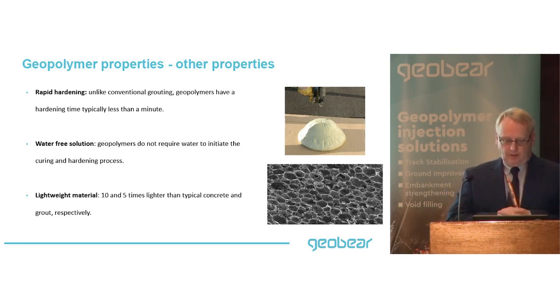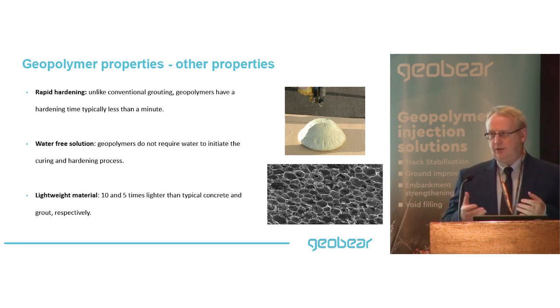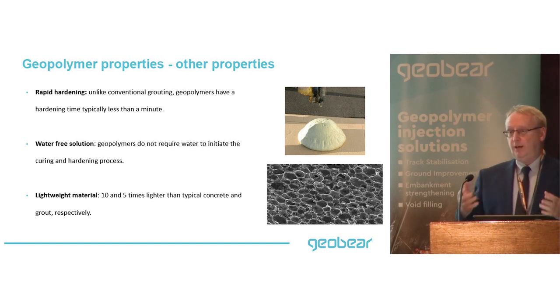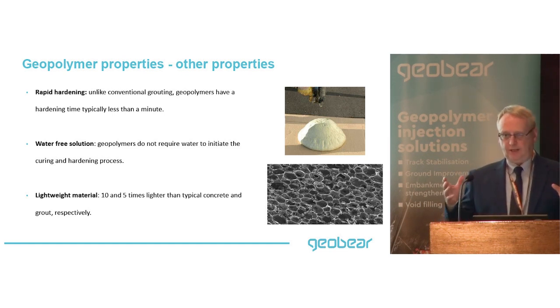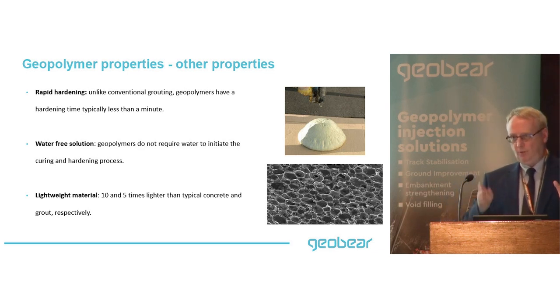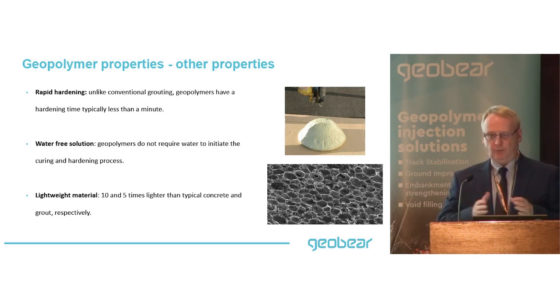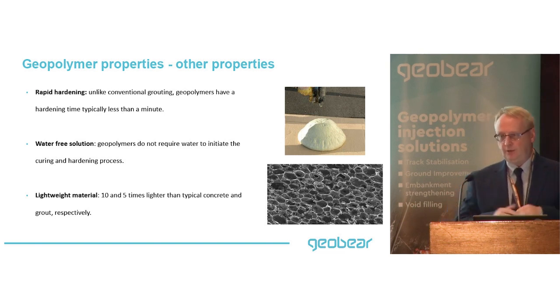Geopolymers do not require water to initiate the curing process, so when you've got a cement-based PFA grout, you generally add water. There's no water added here. We bring to site two liquids, one the resin and one the hardener, and they are mixed at the point of injection under pressure and injected straight into the ground. There's no added water put into that process.